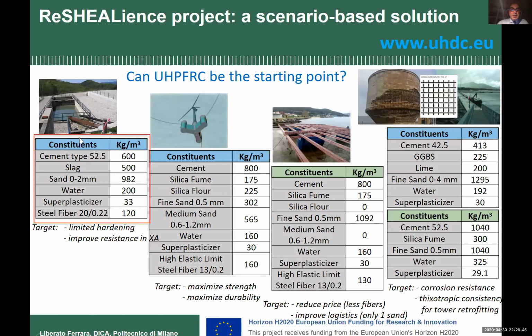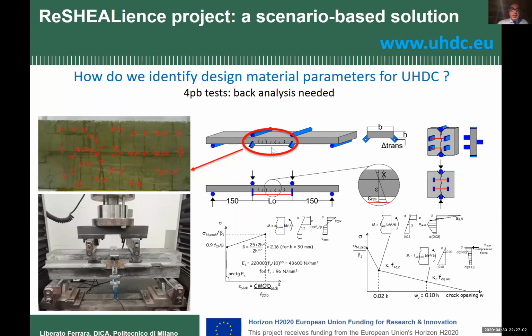That is the one we worked on directly with my group at Politecnico di Milano for the pilots located in Italy. We started by characterizing it. We cast some thin beam specimens and tested them in bending, and we obtained multiple cracks. You can see on the scheme, and also in this figure on the top left, how many cracks developed in a 20 centimeter space.